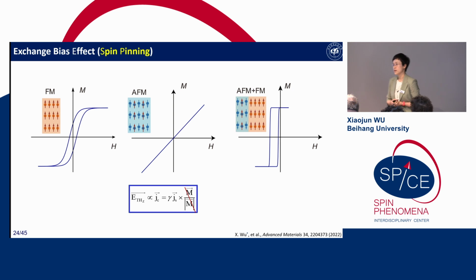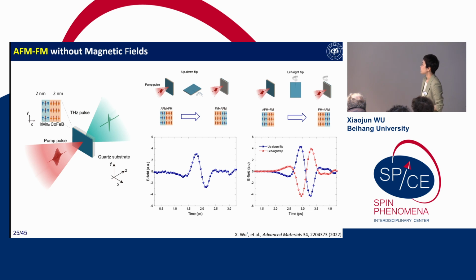So this is the main topic. There is an exchange bias effect, which we call the spin pinning effect. We can directly attach an AFM on the FM, and then the AFM will try to pin the FM, so that we do not need the external magnetic field, and we can directly magnetize the ferromagnet. To demonstrate this idea, we choose iridium manganese to attach on the cobalt iron boron. The optimized thicknesses here we choose as 2 nanometer and 2 nanometer. And for this one, we do not use the external magnetic field.